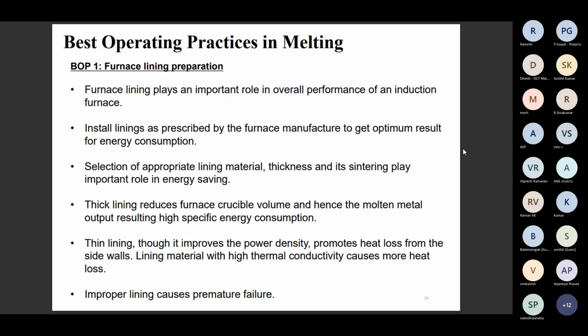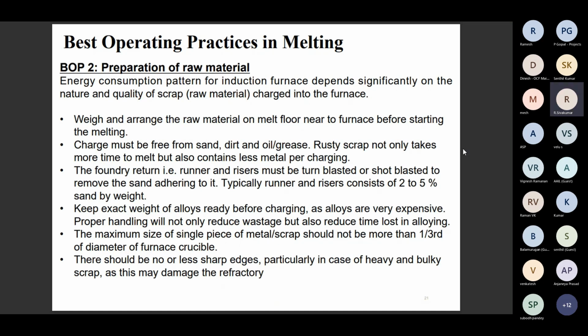Second one, preparation of raw material. The energy consumption pattern for induction furnaces depends significantly on the nature and quality of the scrap and raw material charged into the furnace. First of all, we have to weigh and arrange the raw material on the melt floor nearer to the furnace before starting the melting. The charge must be free from sand, dirt, and oil and grease. Rusty scrap not only takes more time to melt, but also contains less metal for charging. It creates a lot of slag formation inside the crucible.